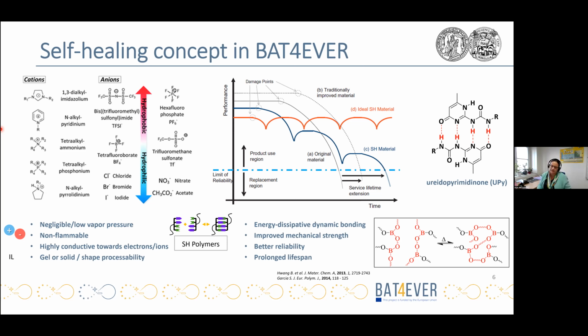So I think that for the lab conditions, it is pretty representative. Personally, I'm not really a fan of only representing self-healing by cutting and then sticking and then, okay, it's healed. I would always include an additional test like mechanical testing, so that the functionality of the materials is tested and compared before and after cutting. So the cutting test alone with a picture of the self-healing material, I'm not a fan of it.